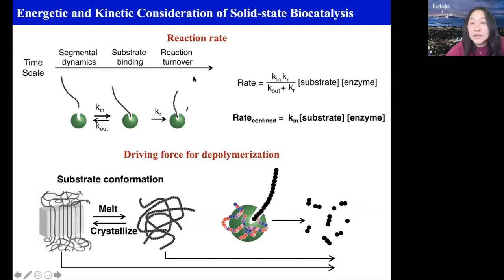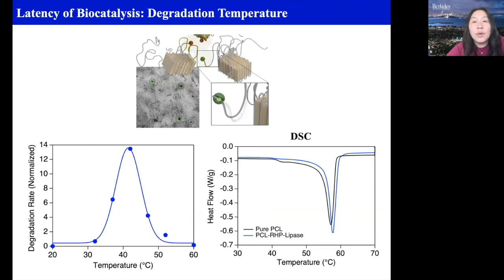On the other end, you have to think about thermodynamics. What is the driving force for the depolymerization? Depolymerization is entropically favorable, so there's a lot of entropy gain for the overall reaction. And in polymers, there's an additional entropy contribution besides just going from polymer to a small molecule, because there's also entropy associated with polymer chain conformation. So if you have a polymer that is highly aligned in the crystalline domain, when it becomes a small molecule, you are going to gain additional entropy. So very counterintuitive: rather than an amorphous polymer, you actually have more entropy gain if the polymer is in the crystalline state.